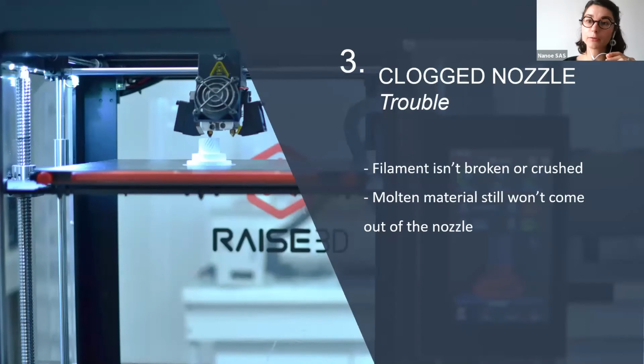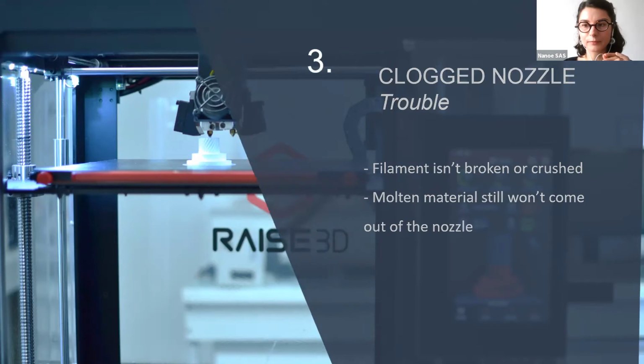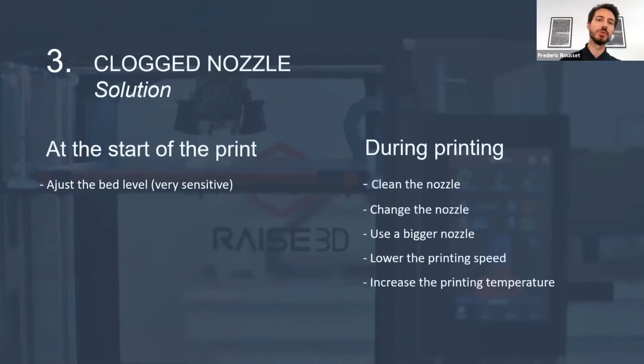So third trouble is the clogged nozzle. If your filament isn't broken or crushed and there is no molten filament coming out of the nozzle, it means that your nozzle is clogged or is likely to be clogged. So Fred, what is the solution for this issue?